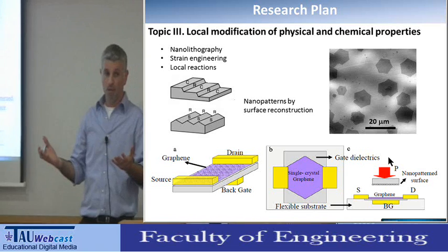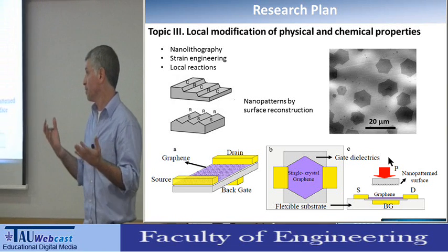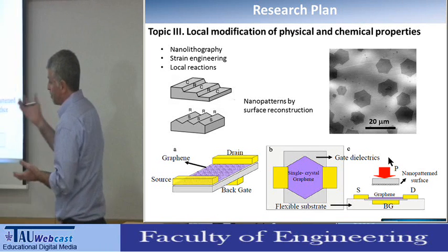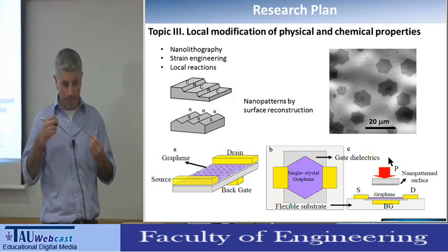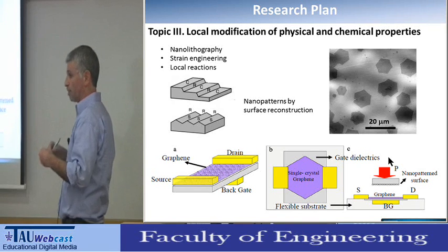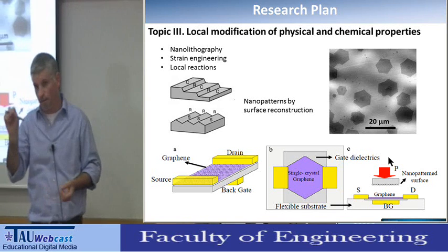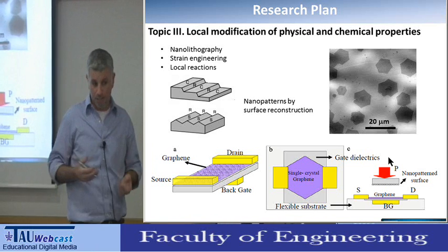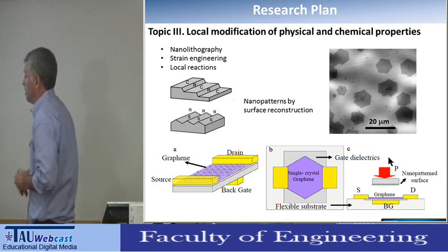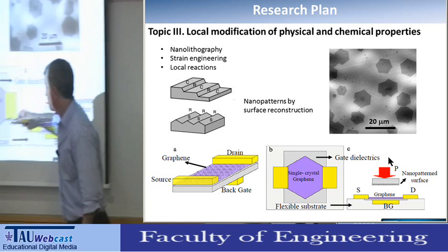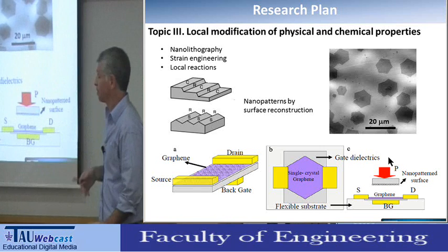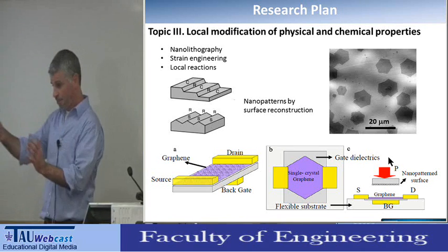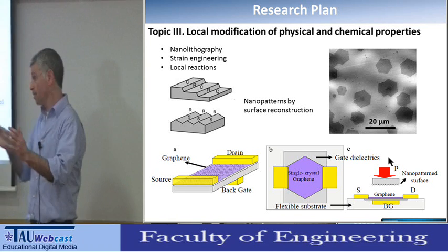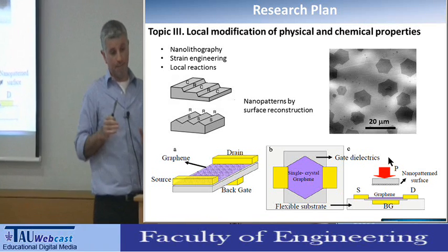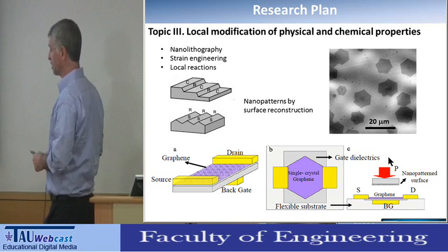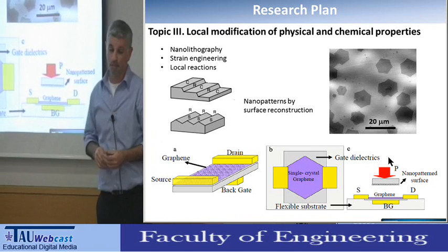First, you can study how these periodic potentials influence the physical properties of these layers, but you can also use them as local points where you can continue and modify those layers very locally to achieve many other functionalities. And you can use, in principle, single crystal hexagons, in this case graphene, but you can use single crystal domains of different materials and study how this periodicity, and how the crystal orientation of the film in relation to the periodic patterning, influence the physical properties.